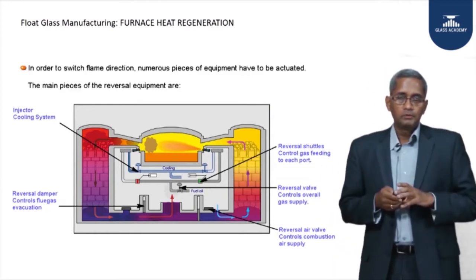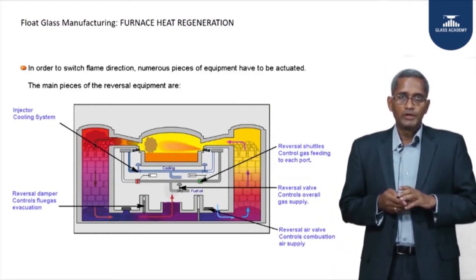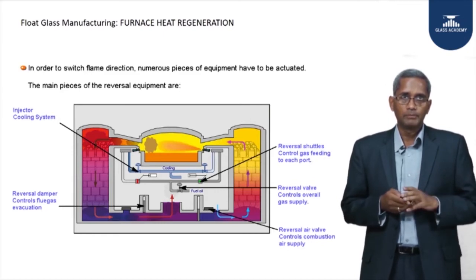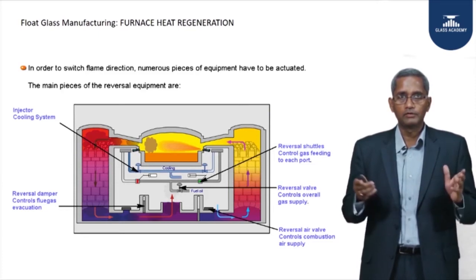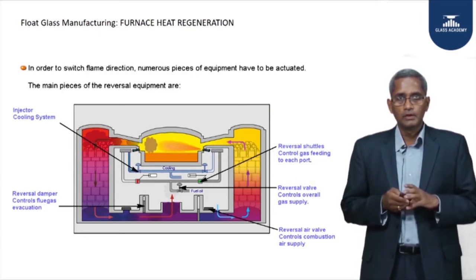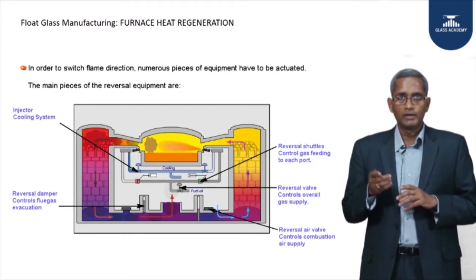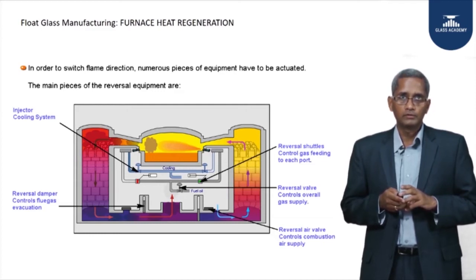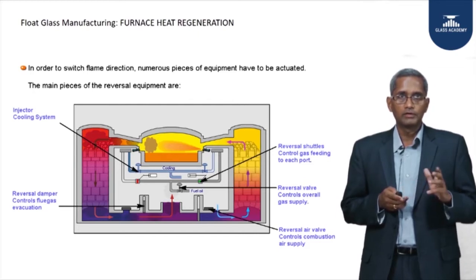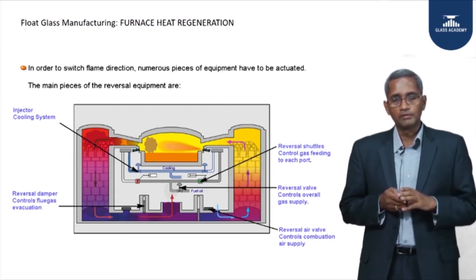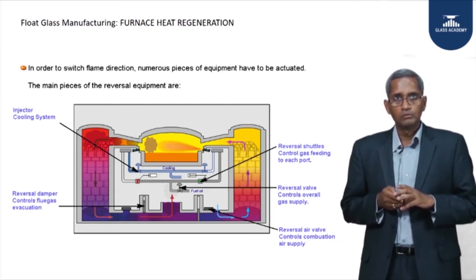Another picture shows how combustion happens more clearly. The furnace is in the middle; the two towers on the right and left are the regenerators. In this picture the firing is from the right hand side, flue gas going through the right hand side regenerators, and waste gas exits on the left hand side — the reddish color at the top of the left regenerator turns blue as it enters the chimney, indicating temperatures have dropped to about 400–450°C.